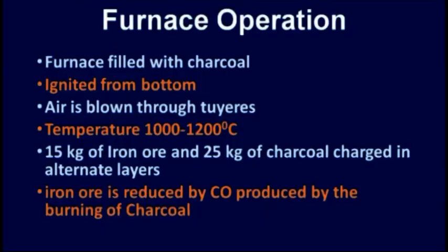Initially, the furnace was filled with charcoal. The raw materials were charged in alternate layers. 15 kg of iron ore and 25 kg of charcoal were charged from the top. The air is blown from the bottom, and so the charcoal was ignited to produce carbon monoxide.